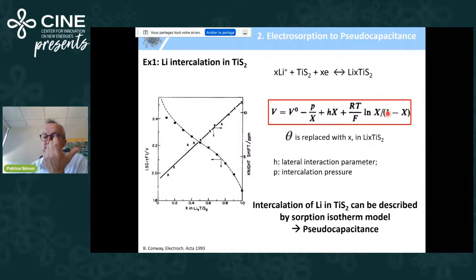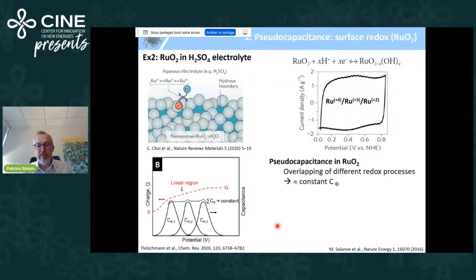And you can see that if you use this kind of a change of potential with x, you depict more or less this sigmoid change of potential with the number of lithium. He also added a kind of lateral interaction parameter, which depends on the h parameter that we saw before, and the internal pressure P, which is the pressure increase when you add lithium into a structure. But the key message is that you can depict the intercalation of lithium in TiS2 using an adsorption isotherm model, and this led to the concept of pseudocapacitance.